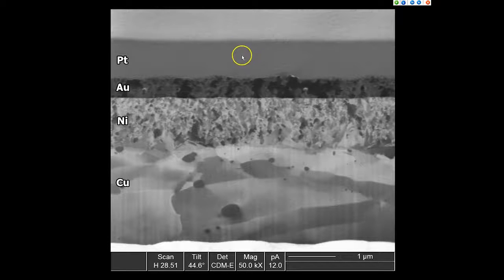And then above that there's a gold plating, which you can see is much thinner than the nickel because gold is expensive, but its grain structure is also fine, which is normally what you see on these types of connectors. A large grain structure gold would be softer and might not be applicable to the application. And then of course we see the platinum we had put on top to protect the surface of the sample.